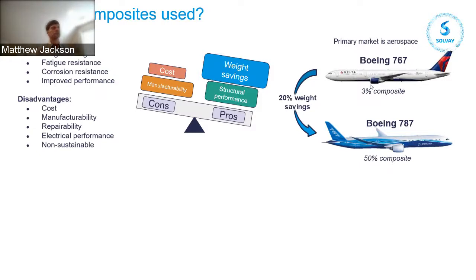And it really has evolved a lot over the last 20, 30, 40 years. And so if you look at the Boeing 767, which was built around 40 years ago, it used only 3% composite materials. The Boeing 787, which was their most recent twin aisle, is composed of around 50% composites. And so by increasing the composites, we can realize a significant weight savings. And again, this can be improved even further by, one, increasing the number of composite materials on the airplane, and two, optimizing and improving the composite materials already. So things like making it electrically conductive, so we don't have to add metal back into the structure, will only allow us to realize higher weight savings.